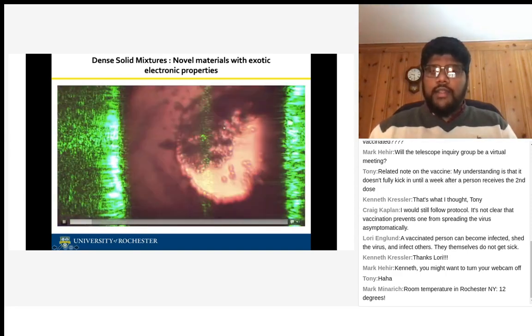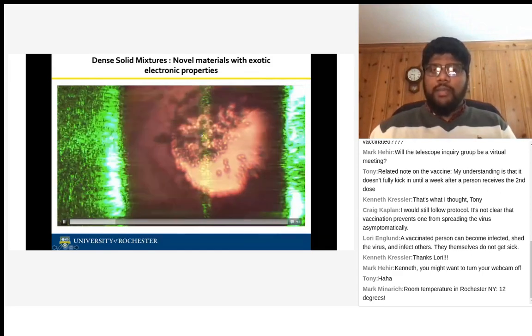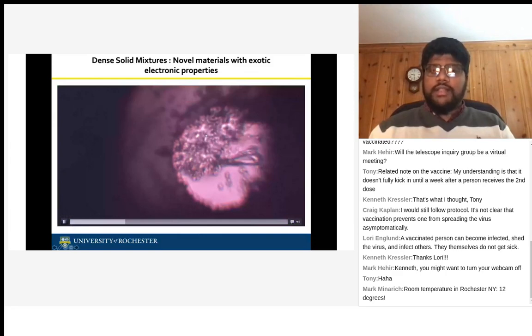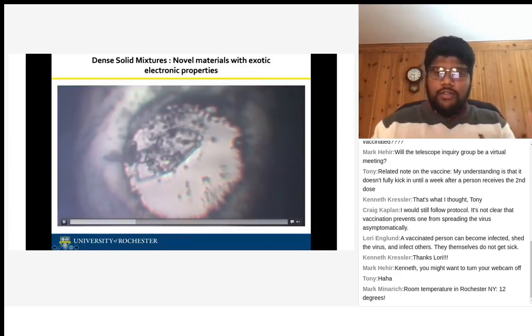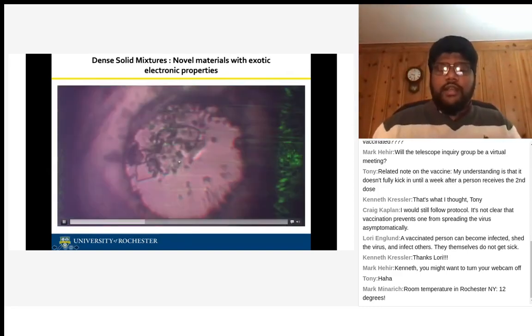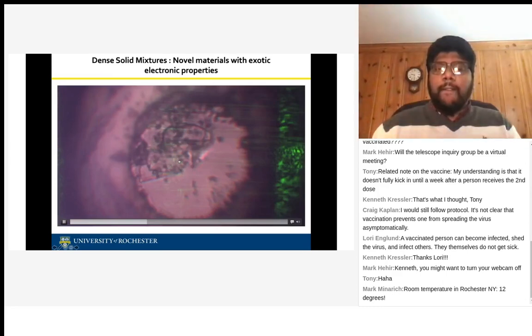All of a sudden, when I shine it, there's a photochemical reaction going on, and then you start to see this opaque area become transparent. See, now all of a sudden it's really a different color, right? It's getting almost transparent. It's no longer opaque. And if you keep shining this, you start to build these different crystals. You start to see a lot of movement here, it's like an explosion. This is under pressure. This is at 4 gigapascal.